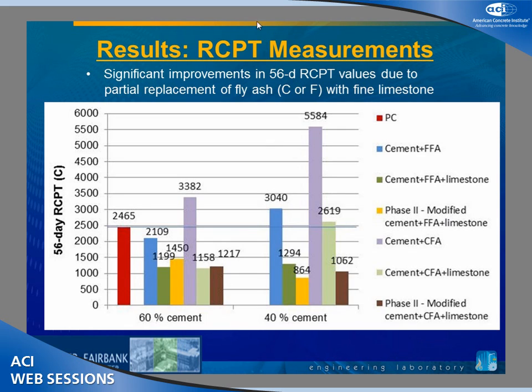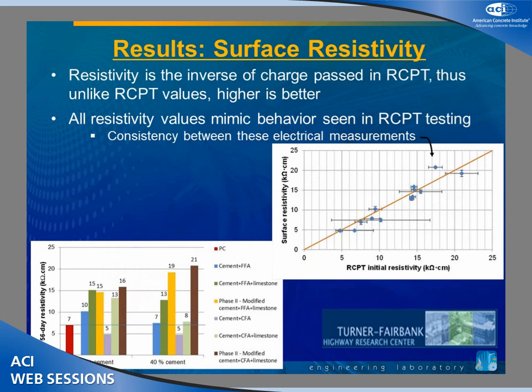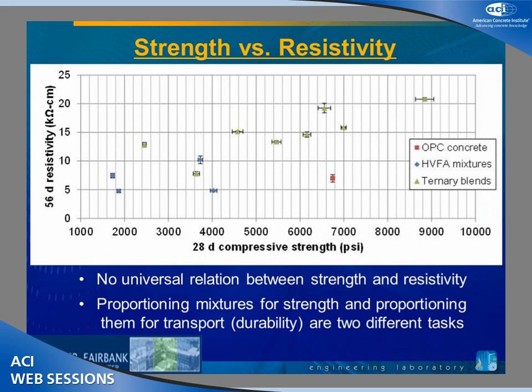And then we can see that as we move, I don't seem to be able to get my pointer anymore, but putting the fly ash in and of itself reduces it, and in every case, when we put in the limestone with the fly ash, like we have 2109, it's cut down to 1199. We see about a 50% reduction in terms of the limestone and the fly ash really working synergistically together. We see the same thing for surface resistivity. I won't go over those.